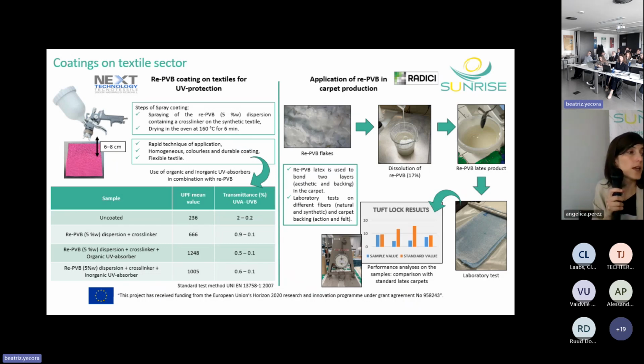And what we can see here are the results of the different textiles and coatings with the values of UPF, mean value, representing the protection versus ultraviolet. And only the coating increases the protection, and with the crosslinkers and the UV absorbers, we have good protection values, and this does not affect the textile.